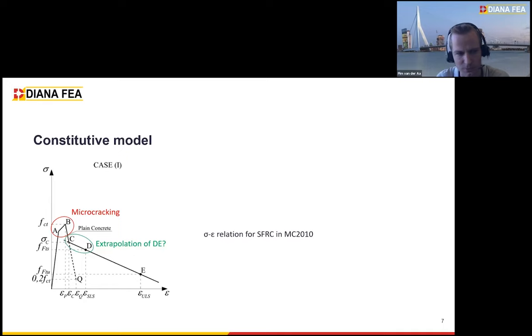Professor De Prisco already explained what point D is and what point E is, but point D is indeed where the CMOD is 0.5 millimeters, and point E is where the CMOD is 2.5 millimeters. To calculate point C, it's basically an extrapolation of point D and E. But what you're also saying is actually that once the cracking starts,